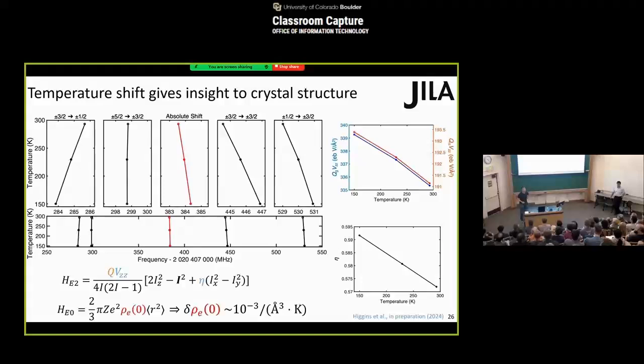So somehow the lifetime you're extracting is not from a spectral measurement, but from just watching it decay? Yes, we actually watched it for about 2 hours.